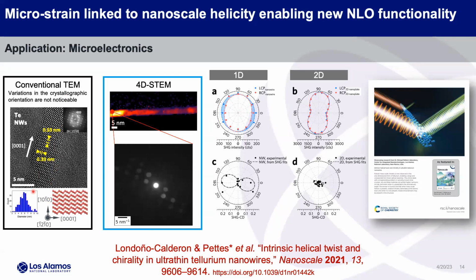the degree of circular polarization difference that was slightly different. I think the highest was 0.2, something like that. But it was much higher than expected. It's because that microstrain forces the structure to relax by torsion, and that gives you the difference in left and right hand circularly polarized light that you can actually measure. And so that's what we're showing here that our artist did for us.